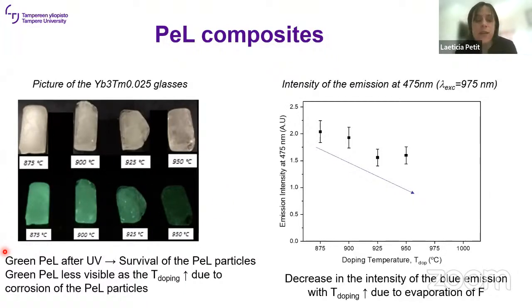As you can see, we have this green persistent luminescence after UV irradiation, confirming the survival of the persistent luminescent particles. But as the doping temperature increased from 875 to 950, we have less intense green persistent or afterglow luminescence from the glasses, and this is due to the corrosion of the persistent luminescent particles I was speaking about. The larger the temperature, the more risk for the particles to be corroded by the glass batch, and then the melting of the persistent luminescence in the glass.